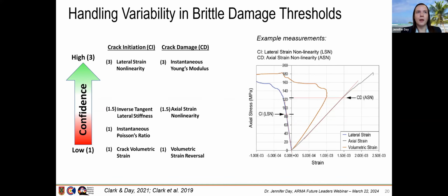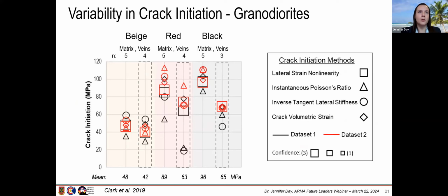When we were then going through and plotting up all of the data, we looked at the variability in the crack initiation and crack damage results. In this case, looking at the beige, red, and black granodiorites, you've got the matrix only samples and then the samples with veins in them. You can see there is quite a large variety within that data. For the purposes of this presentation, I've put the means of each of them at the bottom. You can see there are differences in the mean CI between the matrix only and the veined rocks. But the really interesting part here is that by layering the confidence rankings of the different measurement techniques, we can progress to not just relying on a mean value, but we can also start to sort the data a bit more meaningfully to select the more representative CI and CD data points for use in application in numerical modeling inputs, for example.